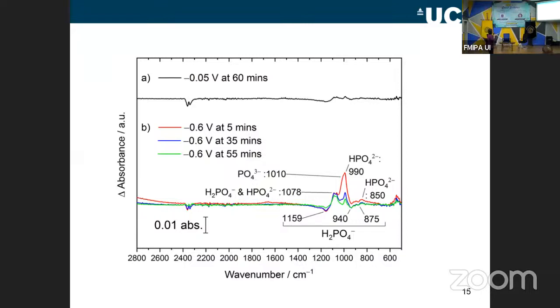Then we apply the potential at which we know the reaction takes place. And you can see that we get changes in the spectrum. And the important thing about the difference spectra is if the peaks go up, it means you have more of that species, or the absorption for those species has gone up. And if it goes down, it means that you have less of the species, and the absorption has gone down. And we're doing this in buffer solutions, as I said, pH 6.8. And these are made up of phosphate species.